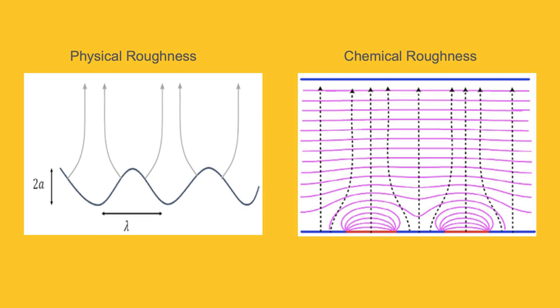One such way to avoid running into these issues is to use photocathodes that are atomically pristine single crystals. These surfaces are very difficult to achieve and typically require repeated cycles where we bombard the photocathode with high-energy argon ions and anneal, or heat, the sample to very high temperatures. Currently, no photoinjector has the capability of performing ion bombardment, and so these single crystal photocathodes are not utilized despite the promise of low MTE.